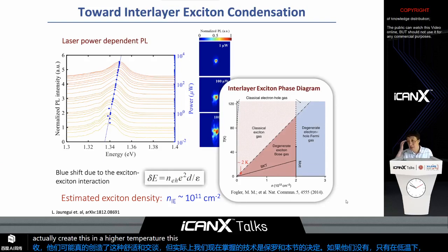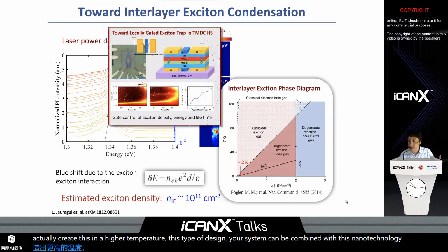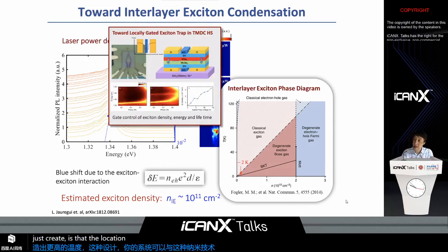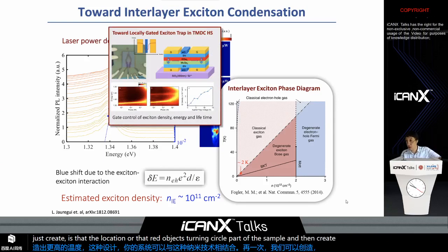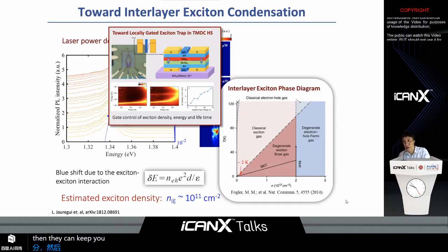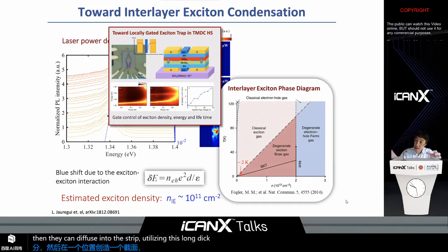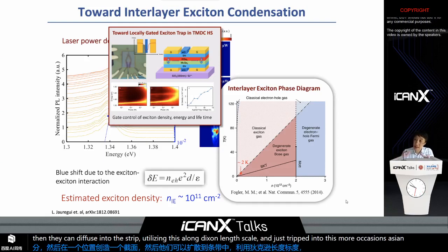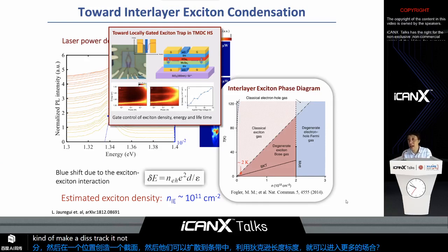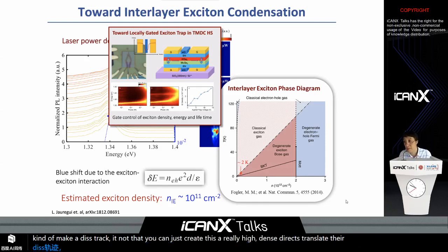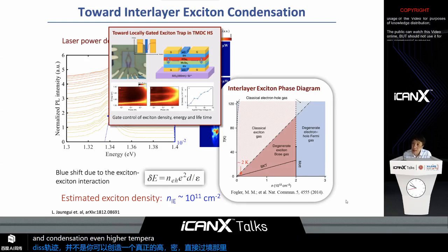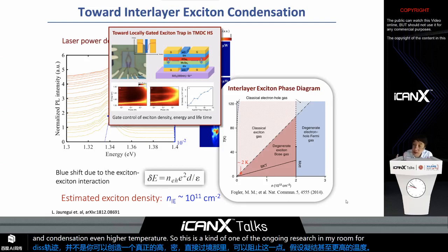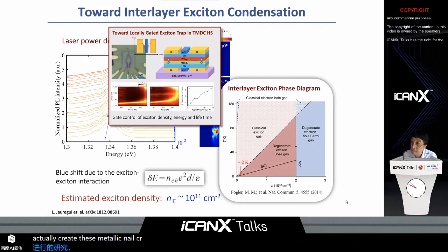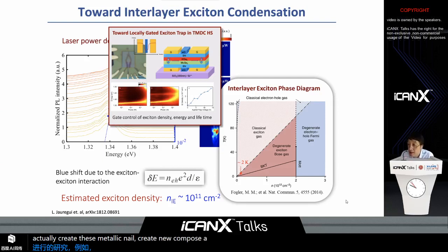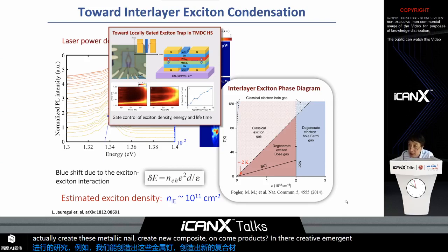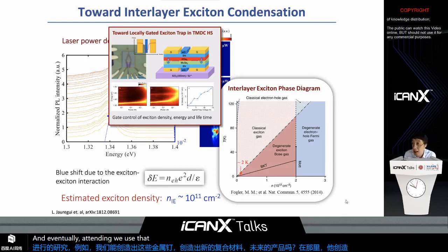This new system can be combined with nanotechnology again. We can create a trap for the excitons in a certain part of the sample, create the excitons in one location, and then they can diffuse into this trap utilizing the long diffusion length scale and become trapped in a small location. If you make this trap deep enough, you can create a really high density of excitons in there, which can boost the Bose-Einstein condensation to even higher temperature. So this is one of the ongoing research efforts in my group: can we create these new composite quantum particles in an atomically thin layer? Can we create emergent phenomena based on that? And eventually, can we use that for interesting future applications?